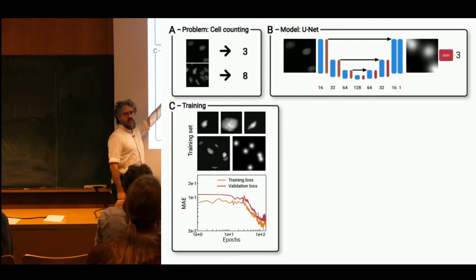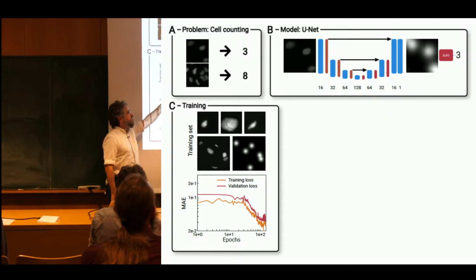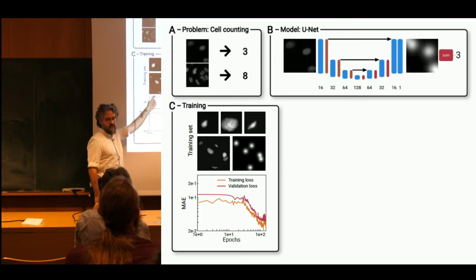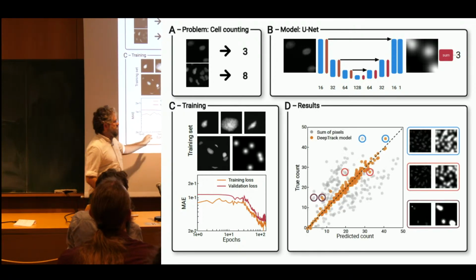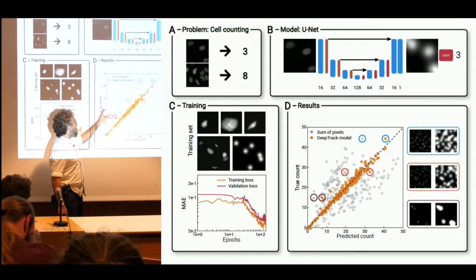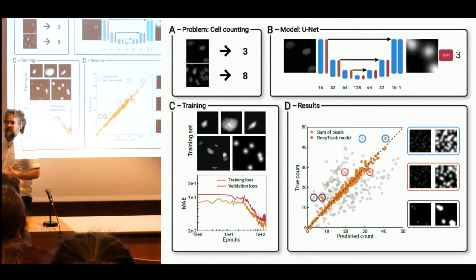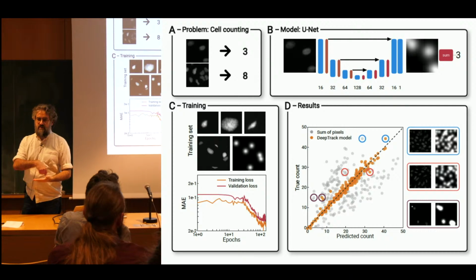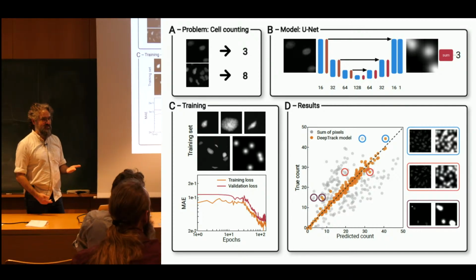And this is done by simulating the cells for the training. So these are simulations done with DeepTrack of the cells. You see how well they are simulated. And then when applied to the real data, it works extremely well. So you see that we have a very, very high correlation between the predicted count and the true count. Since this was a challenge, some biologists actually counted the cells one by one.